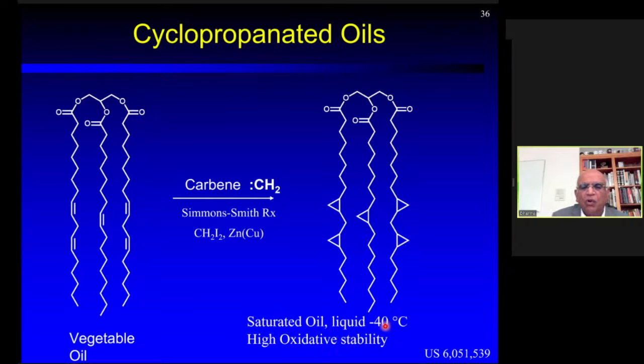This material is flowable up to minus 40 degrees centigrade. Because this is saturated, it has very good oxidative stability as well. So we solved the problem of both the oxidative stability as well as low temperature flow properties simultaneously. So it was very successful, we thought. However, we were not able to commercialize this material, because the cost of this material, because of the expensive reaction, is prohibitive. This is something akin to the operation is successful, but the patient died.